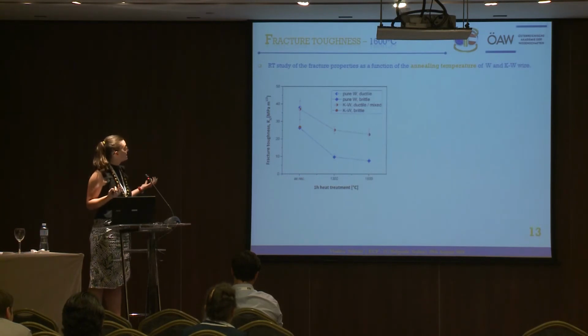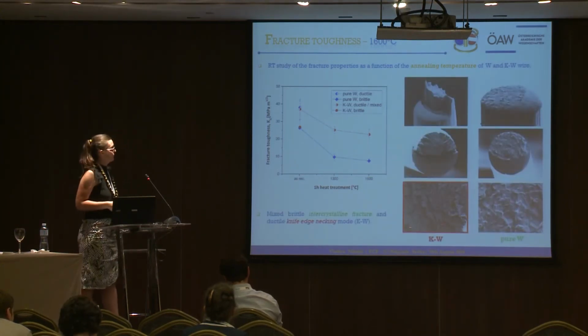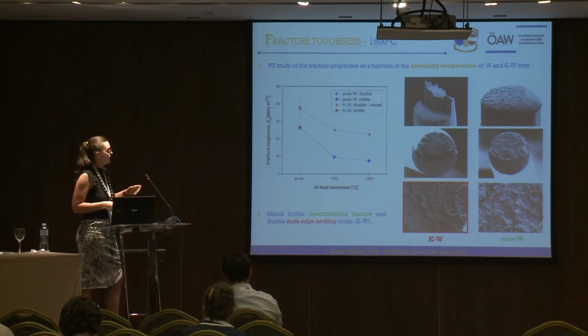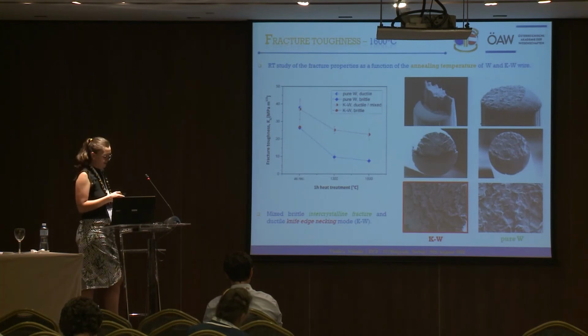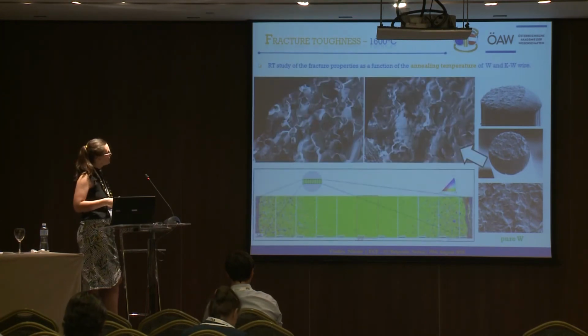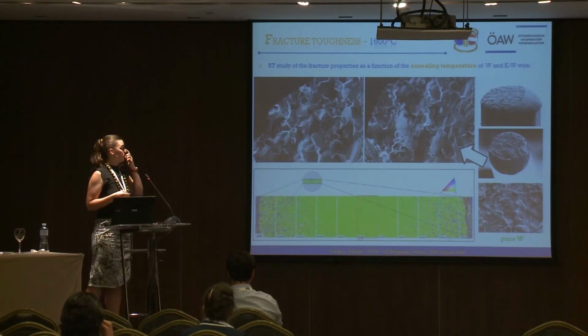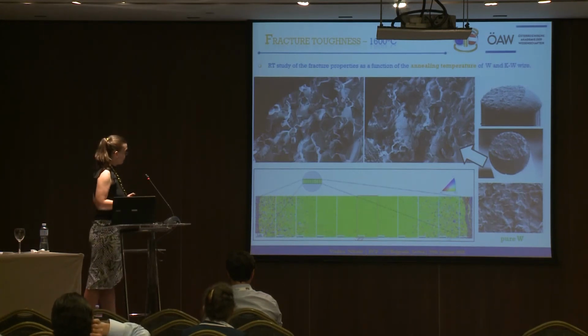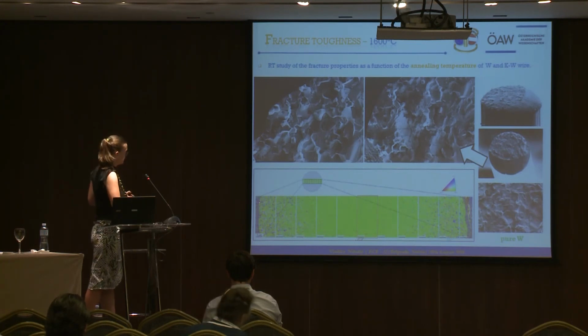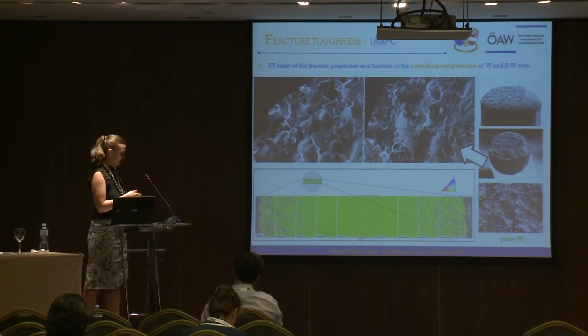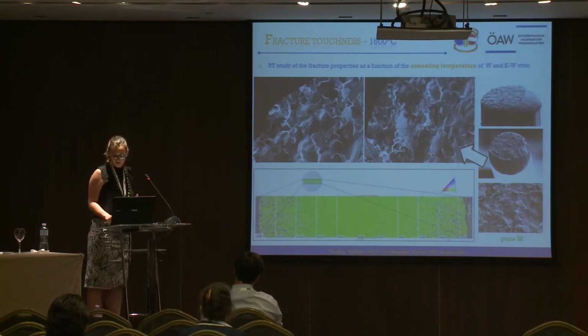And now if we go to 1600 degrees C, toughness decreases even more. In the case of the doped material, these areas of cleaved grains, so brittle areas, increased in their size. And for the pure one, we see a pretty similar picture with an increase of this intercrystalline failure mode, which is somewhat localized at the edge of the wire, which was also anticipated to some extent from this overview EBSD scanning across the entire cross-section. So here we see the entire wire. And we noticed before that there is some localized variation in crystallographic orientation. So it was somewhat anticipated.